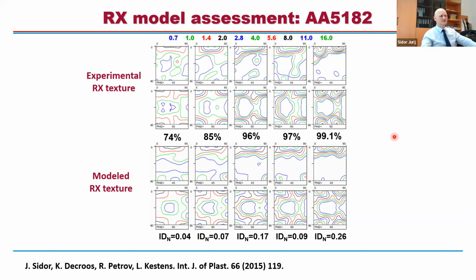This was a special alloy because it contained a lot of particles. So PSN, particle stimulated nucleation, was prevailing in this case. And at lower thickness reductions, like 74%, we had quite continuous theta fiber. And then by increasing the rolling reduction and subsequent recrystallization, we observed concentration of rotated cube texture components, right? We see two strong peaks here in the 45, again in the 90 degree section. And it could be very nicely reproduced by our recrystallization model.